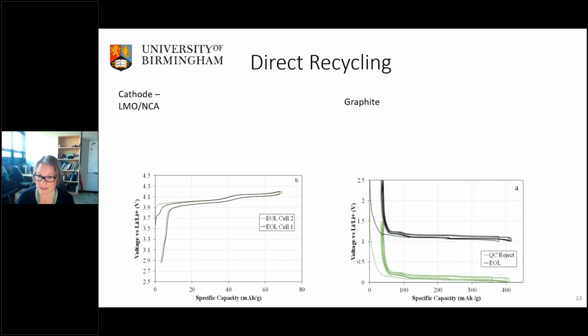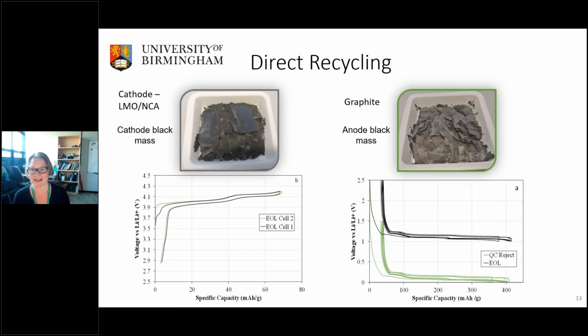So first of all, we looked at direct recycling of these materials. This is how the materials are reclaimed. They're reclaimed in kind of flakes off of the current collector. There's still some binder in there. Now that binder needs to be removed somehow before it's useful. Quite often it's just burnt, its polymeric binder PVDF. Unfortunately, this produces HF, which is not very nice, so other ways of getting rid of the binder are preferred. If we could wash it out with water, that would be even better. And so a lot of work is going into water-based binder systems that we can actually use to design the cell for recovery and recycling, as well as lowering the cost of manufacturing.